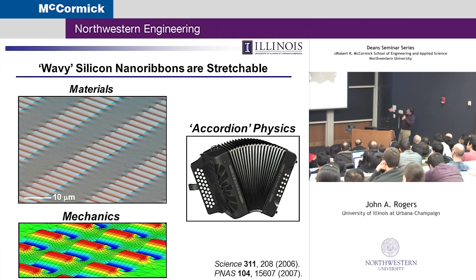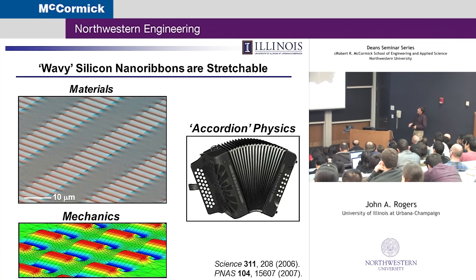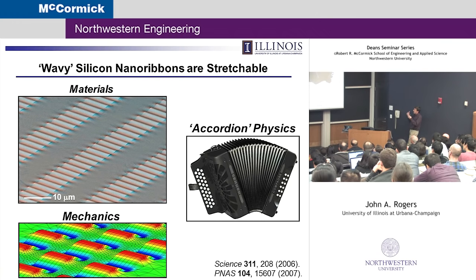then when you relax the pre-strain, it puts the silicon in a state of compressive stress. That silicon responds to those compressive stresses through a nonlinear buckling instability that creates this wavy accordion in physics, in this very hard, soft, integrated material system. Think about this as almost a composite. But the beauty of this kind of geometry is now the out-of-plane deformations can accommodate large in-plane strains in a way that avoids fracture in the silicon itself.